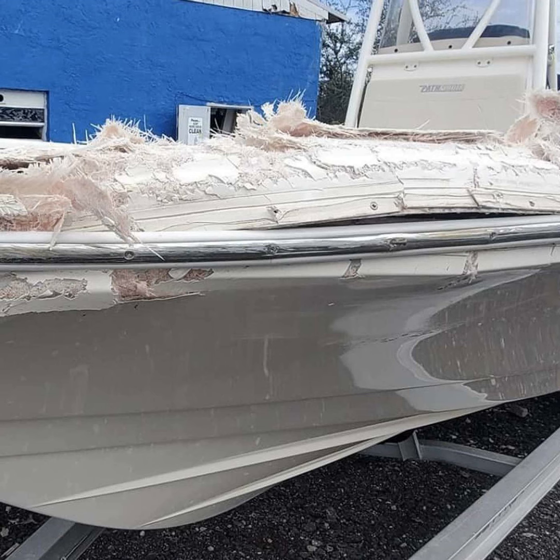Then take yourself some big patches of fiberglass, 1708 or 3610 or whatever you have around, or some thick structural glass. Layer a couple of layers together, wet them out, and stick them on the backside of that damage. Let that cure. And now you can address the rest of the whole repair from the front side. You've got some structure on the backside.